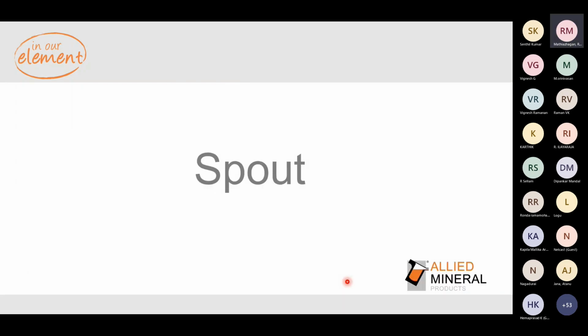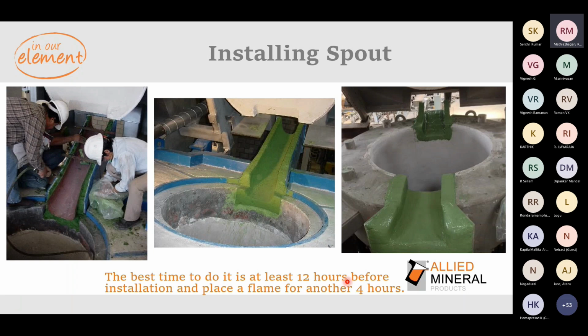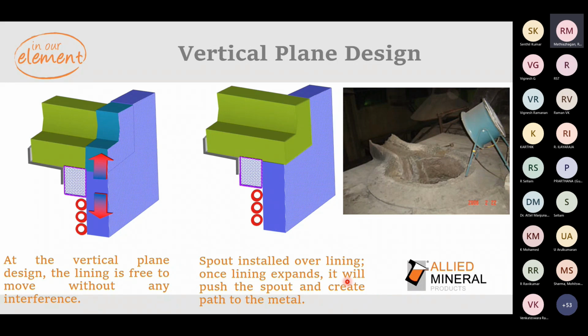So now I'm moving on to spout. We always recommend spout to be done prior to the working lining. This will help the main lining to expand and contract with no hindrance. This will reduce the maintenance in that area and avoid metal penetration happening below the spouts. So as I said earlier, if the spout is done after the working lining, when the expansion and contraction of the main working lining happens, there will be a crack between the spout and the main working lining, which paves a way for the metal to penetrate. So always do the spout first.